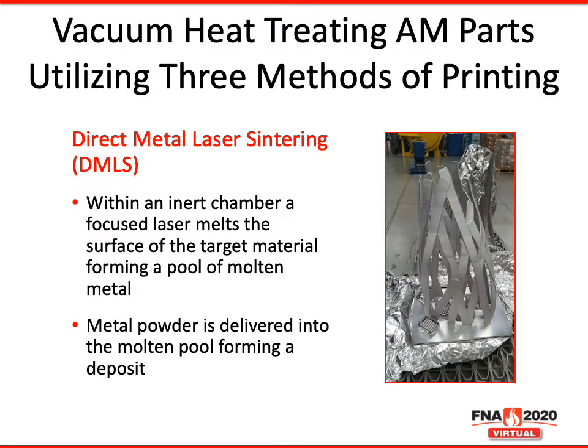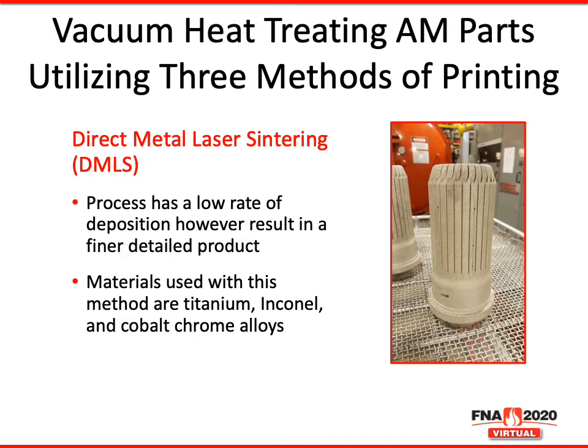So here's a picture of a direct metal deposition process. This is done within an inert chamber. A focused laser melts the surface of the target material, forming a pool of molten metal. The metal powder is delivered onto the molten pool, forming a deposit. This particular part in the picture that you're looking at is a piece of titanium 6Al4V. This is printed hollow. It's roughly 4 feet tall, and this was actually used as a decorative piece for a yacht.